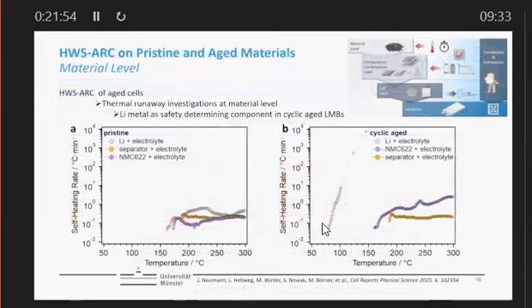Okay, we start simply with looking at heat-wait-seek accelerating rate calorimetry tests on pristine and aged materials, left pristine, right cyclic aged. And we see for the pristine materials, the lithium metal reacts first with the electrolyte, but everything else is in a similar range. Okay, lithium metal is determining the safety. It's the lowest one, with the highest reactivity with the electrolyte, but the others are very similar. And everything happens at 150 degrees C plus, when the lithium becomes soft and the SEI becomes soft.